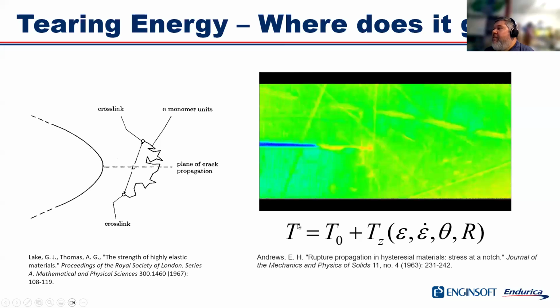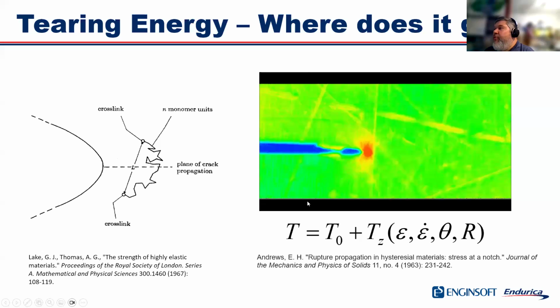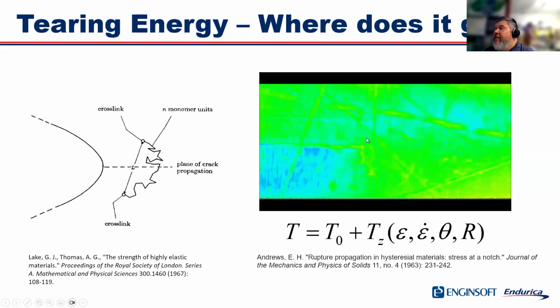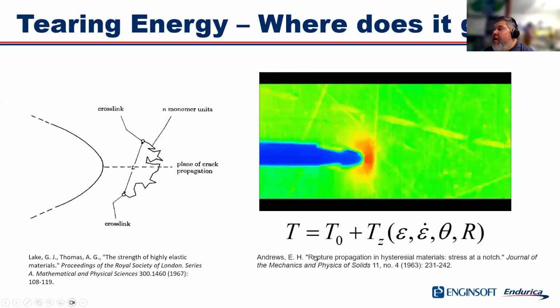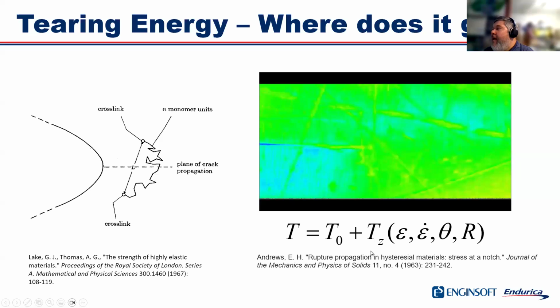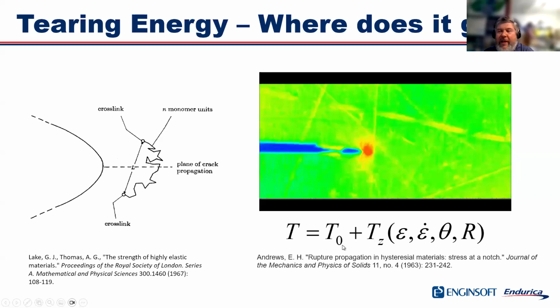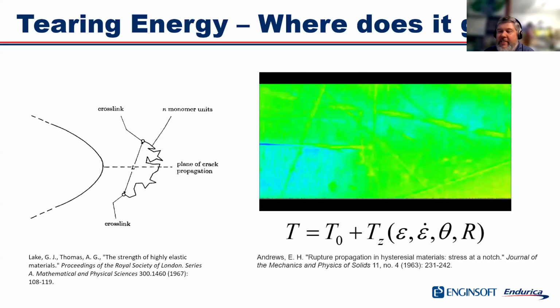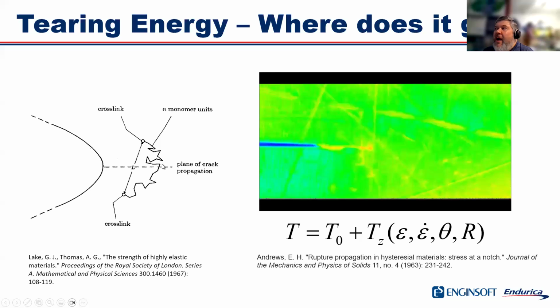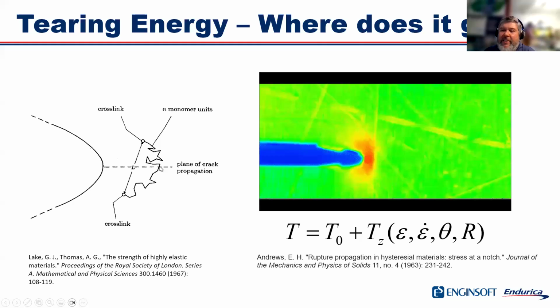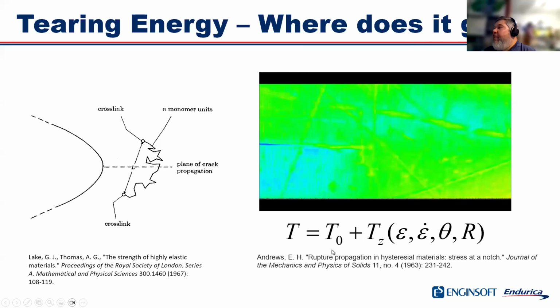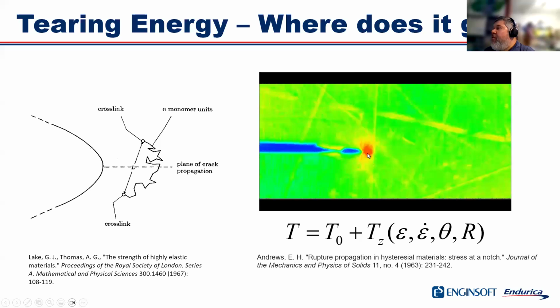So if you imagine a crack growing at a constant rate, the energy required comes from two places. First of all, it's the chain breaking energy, but then it's also the energy that it takes to power up that crack process zone. And what we know about rubber is that this chain breaking energy is actually independent of temperature and rate, and all the complexities that we normally think of with rubber. It's just a constant, right? It's related to the strength of the carbon bond and how many you have per cross section. So it doesn't depend much on temperature. But the temperature and rate dependence of rubber's strength and fatigue properties really comes from the viscoelastic behavior in this crack tip.